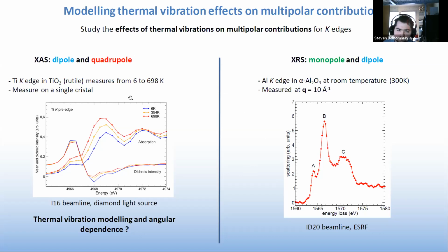And on the second case, this time we have X-ray absorption spectroscopy, so dipole and quadrupole channels. We have the measure of the Ti K edge for several temperatures ranging from 6 to almost 700 K. And this time the measure is done on a single crystal as opposed to a powder here, because there was a very specific experimental setup that allowed us to measure not only the spectra and its temperature dependence, but also the temperature dependence of the anisotropy of the 3D states.